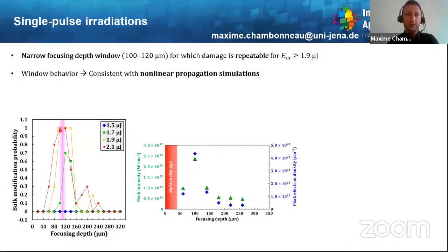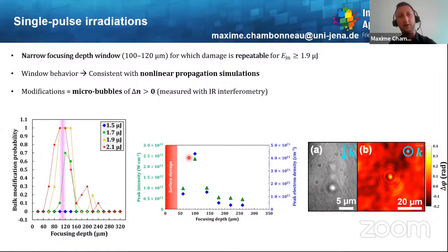So this window behavior shown here was extremely consistent with a nonlinear propagation model, which was developed by my colleagues that I will acknowledge at the end of my talk. And by performing those nonlinear propagation simulations, we were able to see that around 100 micron focusing depth, both the theoretical peak intensity as well as the peak electron density should be enhanced compared to other focusing depths. Finally, we have characterized the modifications by different means, shadowgraphy, as you can see here, and also infrared interferometry, which allow us to conclude that the modifications that we produced consist of micro bubbles inside the material with a positive refractive index change.